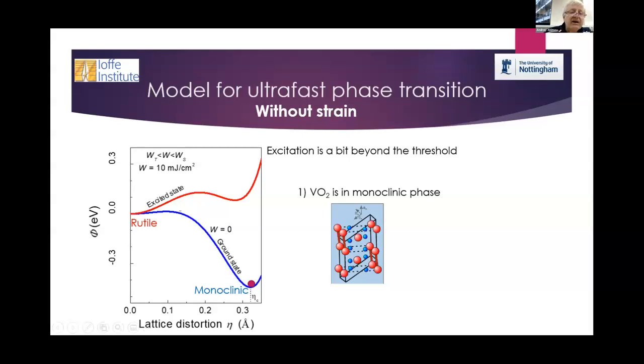So there is this energy, the full energy of the system. The blue curve is the ground state, and you see the lattice is distorted relative to the rutile phase. Then the red curve is the excited state, when electrons and holes are excited, the system is in the excited state.